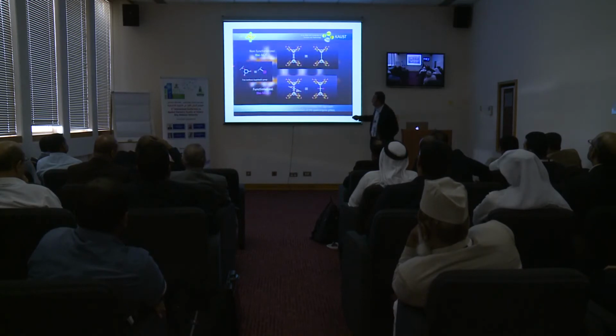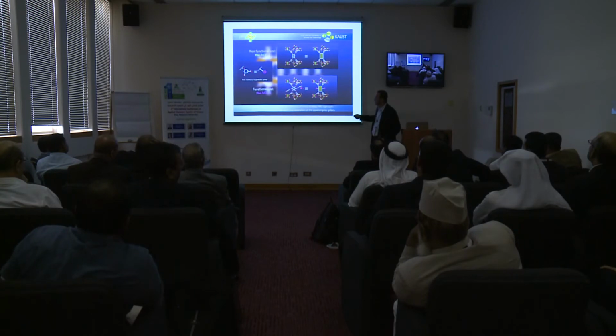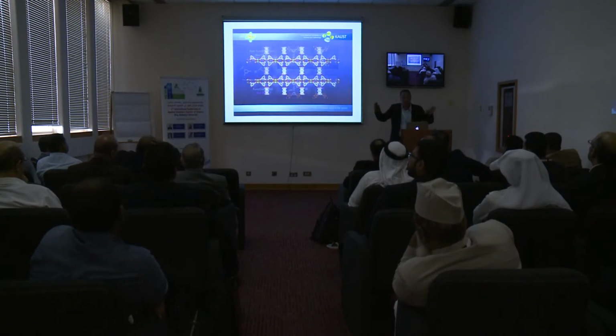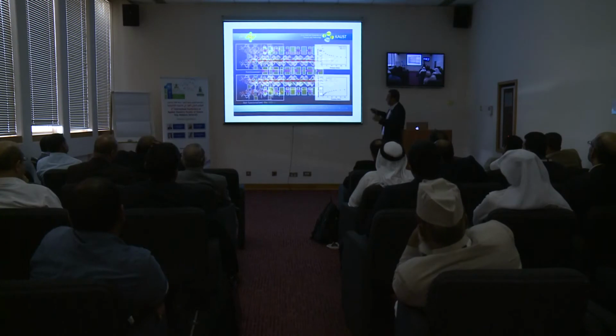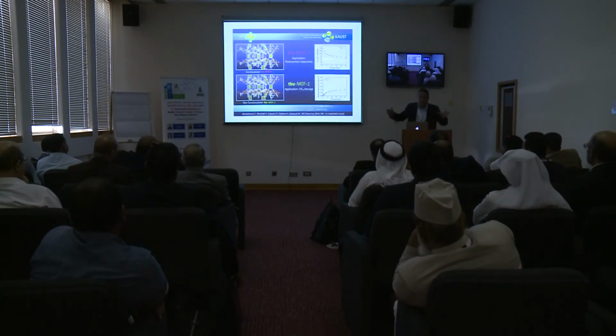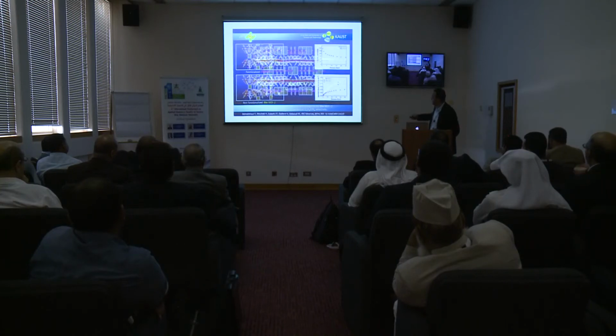So now, if what I said is true, I can put an extra benzene dicarboxylate in here, and I should get exactly the same structure. And that's exactly what happened. We have 3 carboxylates aligned in the channel. They don't interact with the coordination whatsoever. And this actually was not noticed by the community because it was hidden in the paper. But you have 3 carboxylates in the channel. Then if you have carboxylates, you can use it for separation. If you don't have carboxylate, you can use it for storage.